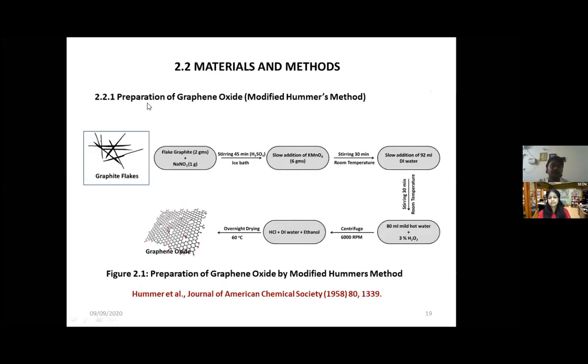First, we prepared a graphene oxide material using the modified Hummers method. We have flake graphite purchased from Southern India Scientific, which is nearby. We powdered that using an agate mortar, and 2 grams of powdered flake graphite with 1 gram of sodium nitrate is stirred in the presence of 60 ml concentrated sulfuric acid for 45 minutes in an ice bath. At this step, we observed a vigorous effervescence, and then we slowly added 6 grams of potassium permanganate and stirred for 30 minutes at room temperature.